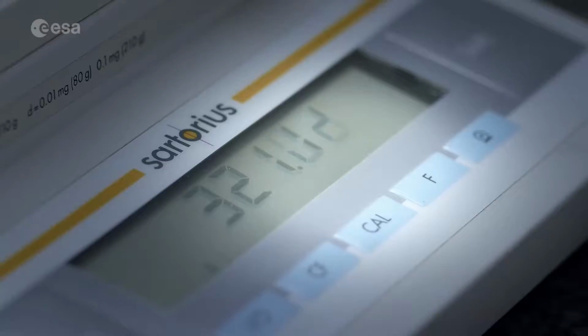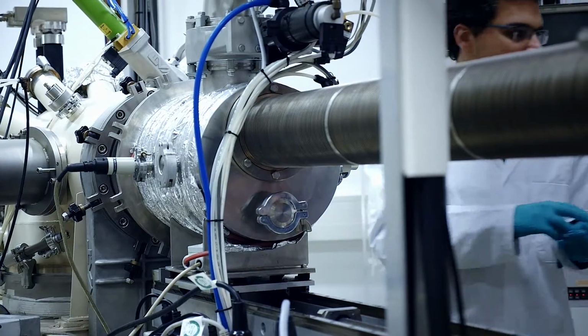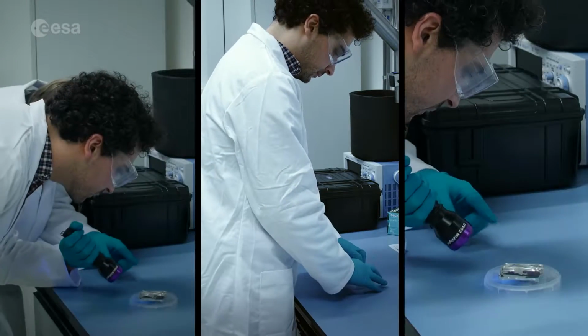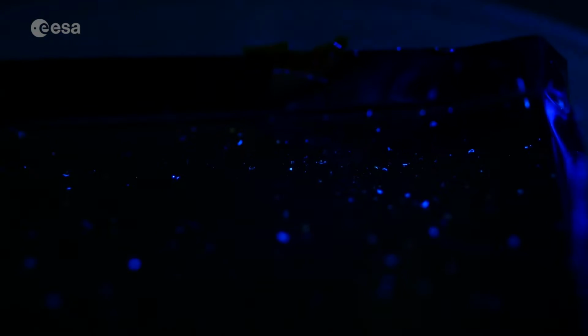After weighing the samples, we noticed that there was a substantial mass loss when compared to the initial conditions. These dislodged particles were collected on a collector plate that was positioned under the beta cloth samples during the exposure. They could be seen with the UV light.